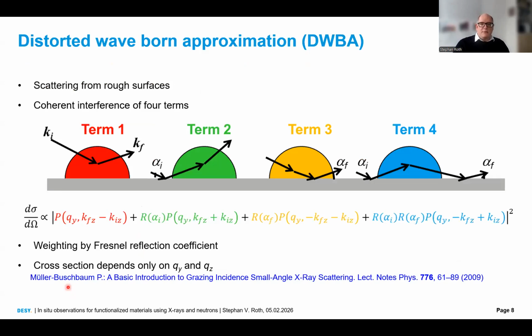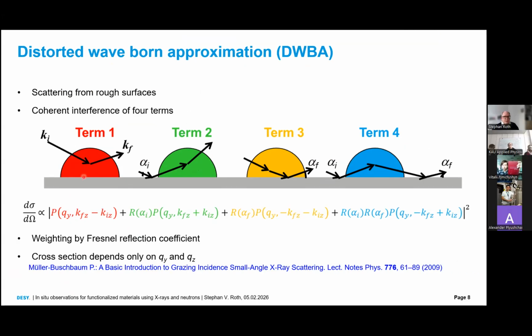So let's start. When you do grazing incidence scattering, your sample is typically lying nearly flat and the X-ray beam is impinging under a low angle, around 0.4 degrees, with X-ray energies in the range of 10 to 13 keV onto the sample. And then the X-ray beam can undergo direct scattering. This is the Born approximation, or it can be reflected then scattered, or scattered then reflected, or reflected, scattered, reflected. And all these four terms need to be taken into account when you calculate the scattering cross-section or the final intensity. And you see here, this is the particle form factor, which we know from classical Born approximation, and this is then weighted by the Fresnel reflection coefficient. And you have to take then into account the changing of the vector direction.